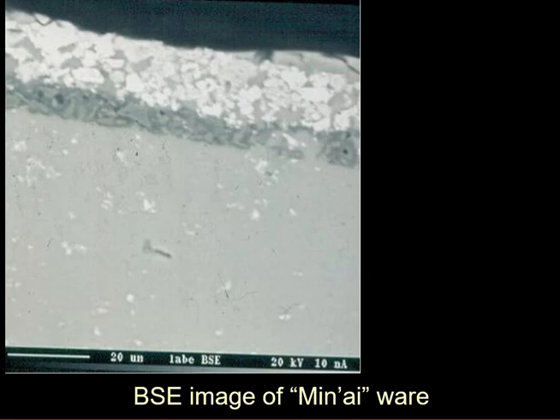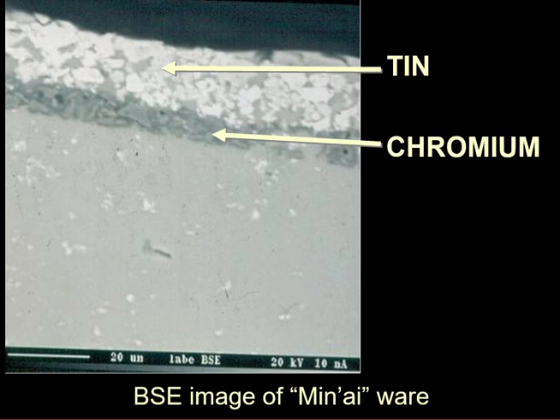In this SEM photomicrograph of a section through a black and white painted region of a Minai ware sherd, you can see the white paint layer containing abundant tin oxide particles, and the black layer containing abundant angular chromite particles over the glaze containing tin oxide particles. So this is a tin glaze, and over this is the black, and over the black is the white. And you can see with the very sharp margins that these were not subjected to a great deal of heat.